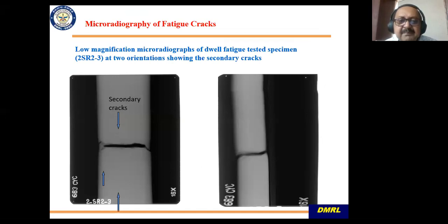Here there is a flat sample which was part of my postdoc work, and which was dwell fatigue tested. This is Ti6242, and you can see the main crack. It is a flat sample, and the image was taken at two different orientations. This is a flat surface, and this is the edge. Micro radiography was done, and along with this main crack, you can also see very fine secondary cracks which are embedded. And we wanted to know what is the orientation around the cracks.